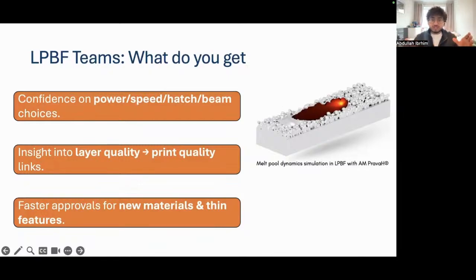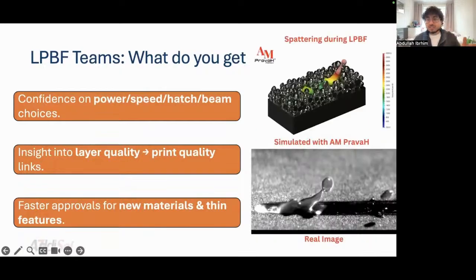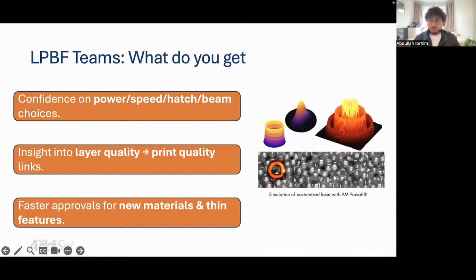The software flags certain regimes linked to keyhole porosity, lack of fusion, and other types of defects like balling on thin features and overhangs. And because the powder quality is modeled, including non-spherical particles and packing, you can see how rough or sparse layers increase the risk of defects before the laser ever moves. On top of that, we can also test different beam profile shapes to widen or stabilize the melt pool on sensitive geometries, and run multi-layer, multi-track windows to check if a recipe can stay healthy as heat accumulates. The net result of all of this is faster approvals for thin walls and new alloys, fewer scrap builds, and a much cleaner sign-off from R&D to production.